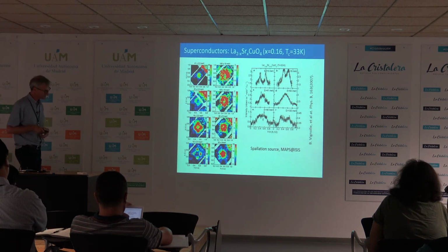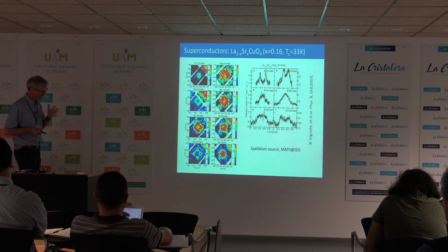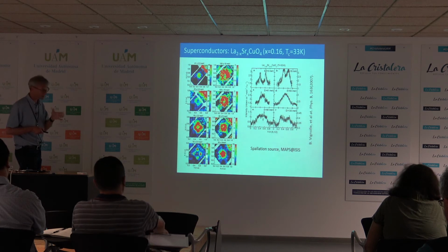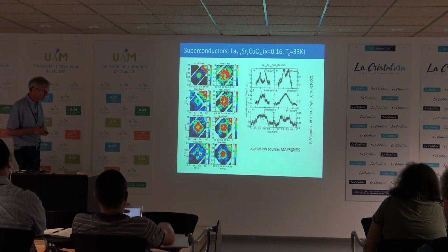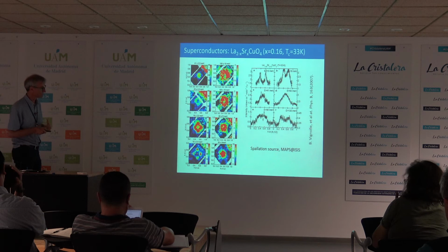But if we're interested in the excitations, if we're interested in the thermodynamic properties at low temperatures, for example, explaining that peak in specific heat we saw, then it's not all this stuff that's important. It's actually the low energy excitations that would determine what's going on. And these are quite sharp, in fact. So the width of these is not a correlation length, it's the width of the response function at low energies. So that can be 10 or more lattice parameters long at low energies.